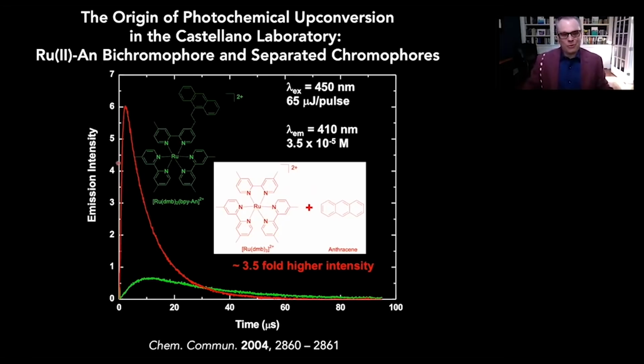And then of course, we were pleasantly surprised that under the same exact experimental conditions, just matching the concentrations, we saw basically a 3.5-fold increase in the delayed fluorescence. This was the first experiment we actually did that demonstrated very unequivocally that you could do photochemical upconversion. And then we recognized, oh, this is pretty exciting.